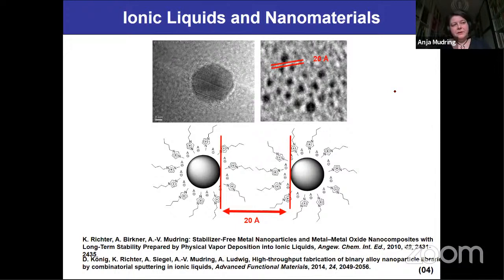becomes also apparent when you look. So on the left, you see one single image in high resolution mode in the TEM. But when you take a step back and look at the larger view, on the upper right image you see the same particles swimming in the sea of ionic liquid. And they really, in 2 dimensions, make a closed packing. And the distance between 2 particles can be associated with the radii of the cations, in that case, because they are the larger ones, of the ionic liquid. So that's something very interesting to know.